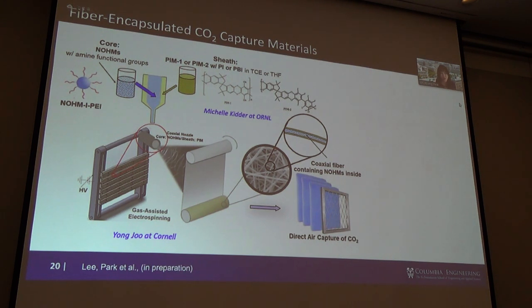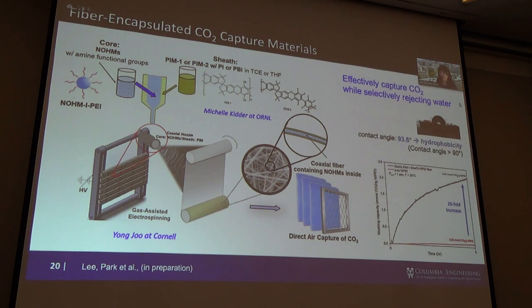So what we envisioned was, well, we like encapsulation, but we want to minimize and control the pressure drop across the direct air capture system. So I started working with Yong Joo at Cornell University and Michelle Kidder at Oak Ridge National Lab, putting these materials together between NOHMs and PIM, which is a highly porous polymer, which we can cure during the solvent evaporation. We electrospun them into furnace-filter-like systems with really low pressure drop. Another benefit was that we selected PIM material because it is hydrophobic. So even during rainy days, we can selectively capture CO2 while rejecting the water, which really improves the overall energy consumption during the solvent regeneration.